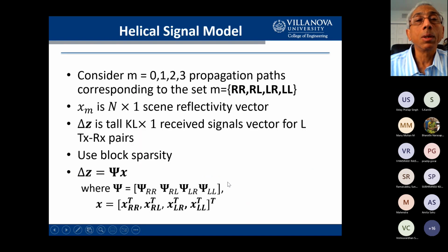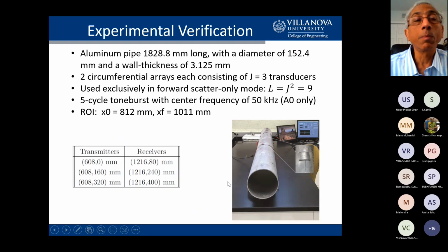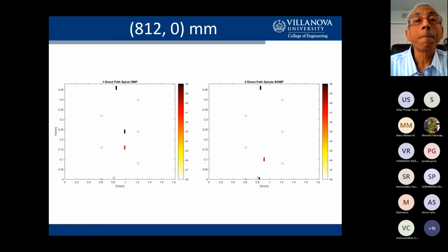I'll skip these details, and just show you the experimental setup. So if you have a defect that's located over here, and you just do one single path, your predictions are all over the place, but nowhere near where the defect is. But if you use multipath modeling, or in this case 4 paths, you can identify where that defect is pretty well.